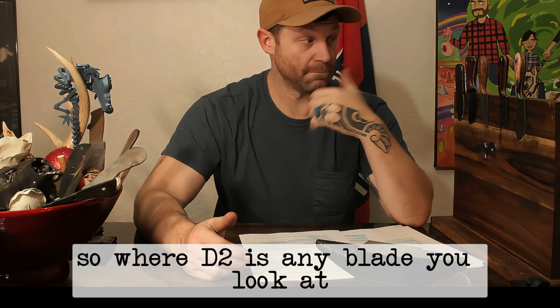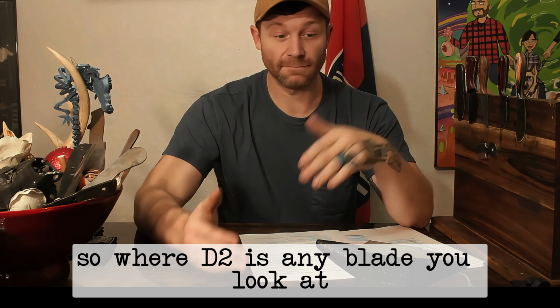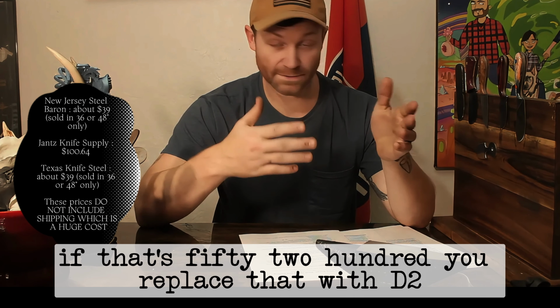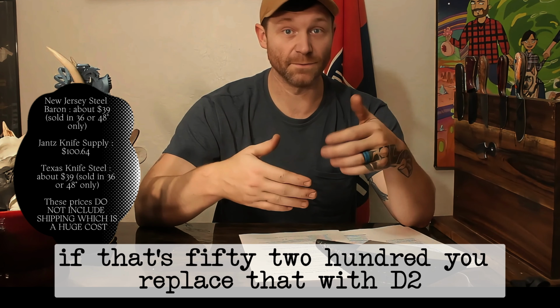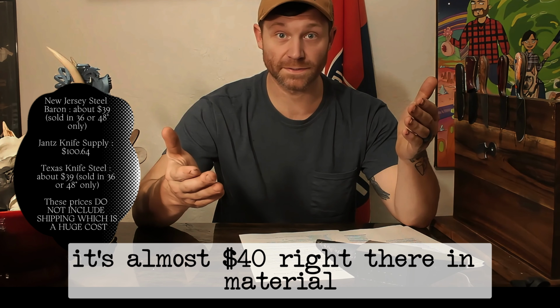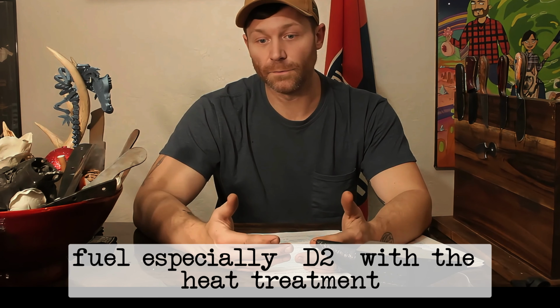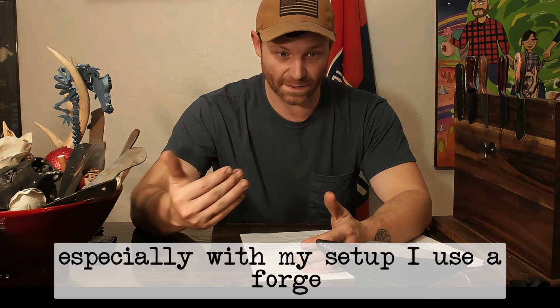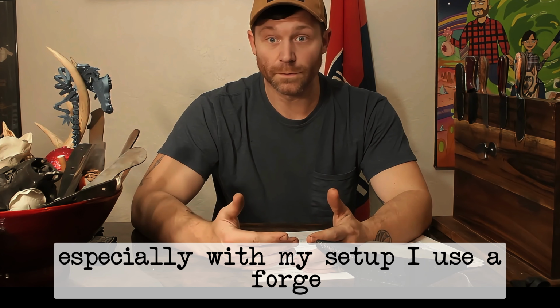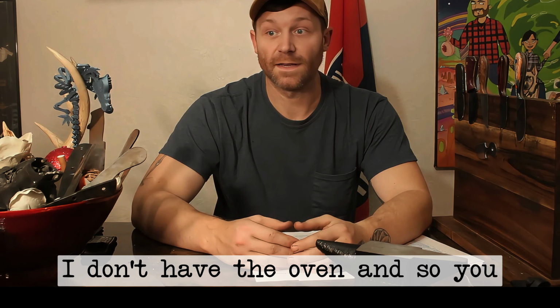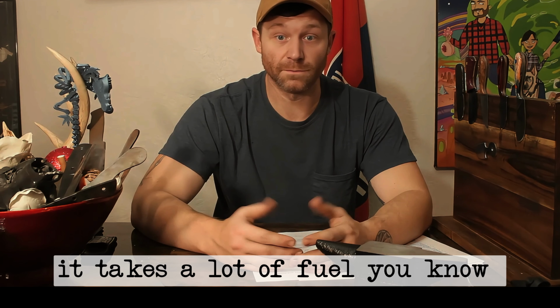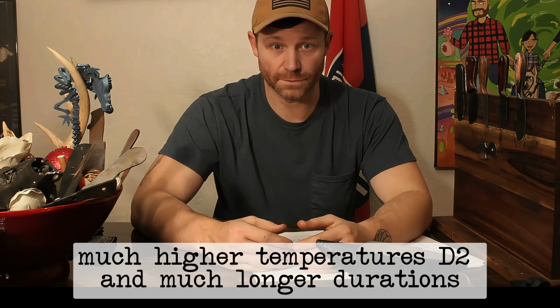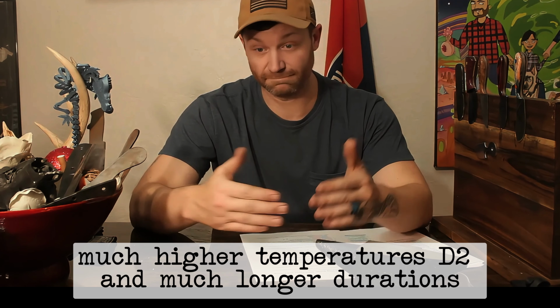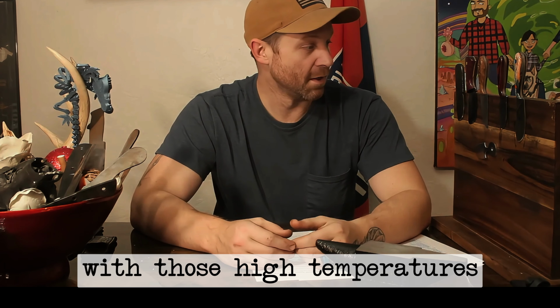And then D2 jumps up higher than that. So where D2 is generally any blade that you look at, if that's 52100, you replace that with D2, it's almost $40 right there just in material and fuel, especially. D2 with the heat treatment, especially with my setup, I use a forge. I don't have the oven, and so it takes a lot of fuel. Much higher temperatures with D2 and much longer durations with those high temperatures.